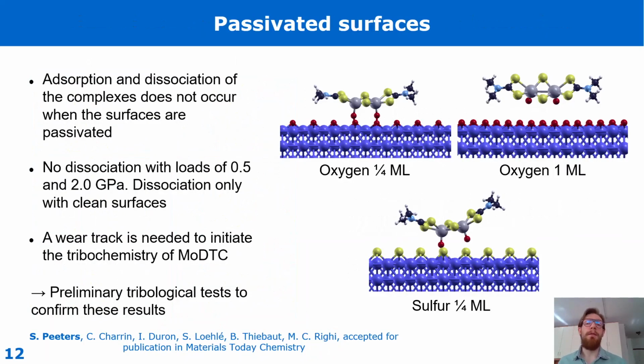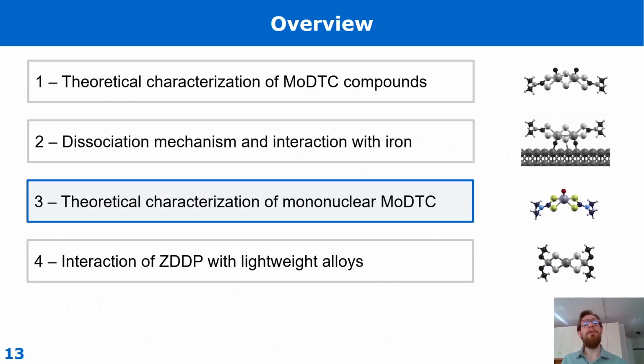Of course, metallic substrates can be covered by passivating layers, and for this reason we considered an iron substrate passivated by 1/4 monolayer of oxygen, a full monolayer of oxygen, and also 1/4 monolayer of sulfur. In all these cases, MoDTC additives struggle to adsorb. Only very weak physisorption is obtained, even in the presence of high loads. And in fact, decomposition cannot occur because the molecular fragments have no free sites to attach to on the surface. Now I'm going to describe mononuclear MoDTC compounds.